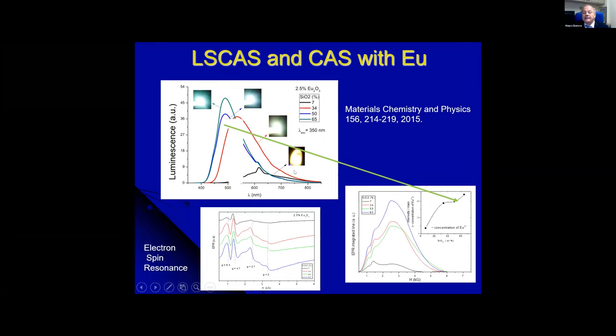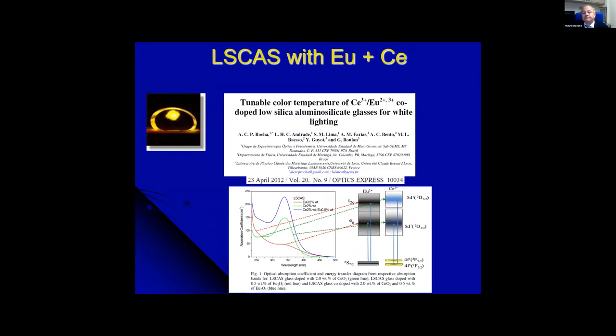You can see here that although we produce europium 2+, which is important for the visible emission, the emission shifts to the blue region when the concentration of silicon is increased up to 65%. This 7% is this yellow emission here. And we also did electron paramagnetic resonance to show that the silica composition controls the oxidation state of europium, 2+ and 3+.